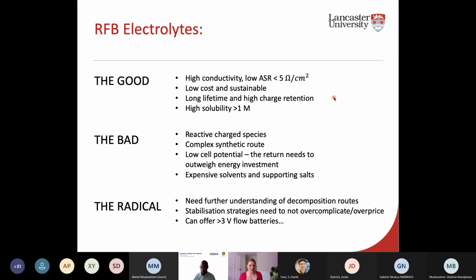So to conclude, the good, the bad and the radical, I can't dictate which is the good, the bad and the radical of electrolytes. The developments are incredible in what's happening in this space. It's really fast moving. But typically you're going to need a highly conductive, low surface resistance solution, at least lower than 5 ohms. And that might be related to your cell design as well as the solution being conductive. So it's not just about the electrolytes here, it's about the design of the cell. You need something low cost and sustainable, and then something with high solubility, as well as high charge retention in its charge state, so a long lifetime, and it needs to stay stable.